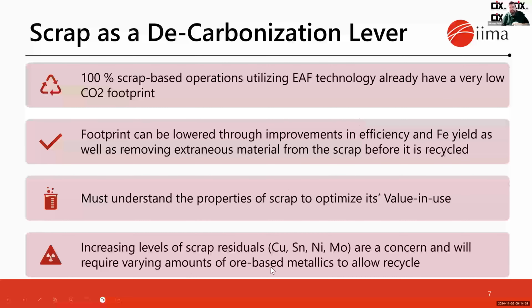As I mentioned, we need to understand how scrap fits into the overall picture, because the future is a balance between scrap and ore-based metallics. So if you look at scrap as a decarbonization lever, 100% scrap operations utilizing EAFs already have a fairly low CO2 footprint compared to integrated plants. But that's not saying that they don't need to do anything. The footprint can be lowered even more through improvements in efficiency and improving iron yield, as well as removing extraneous material from the scrap before it's recycled. So we really need to understand the properties of the scrap, its value-in-use. And what we're fighting is that we are seeing increasing levels of scrap residuals, and we need to find a way to slow that down.